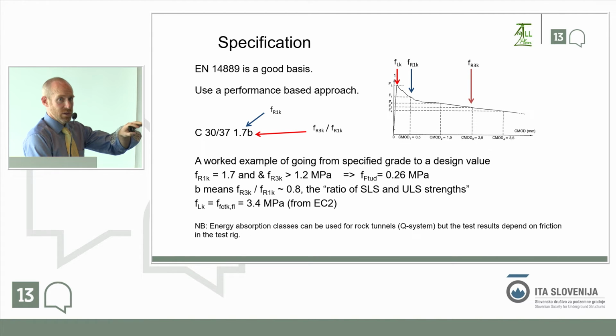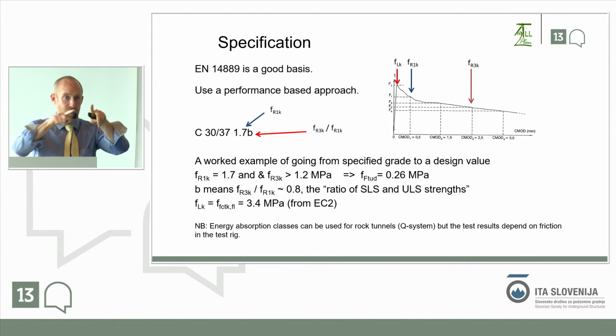So that's 1.7 in this case. And then in terms of this slope, we call it a class B. So that means that the minimum strength at FR3K would be 0.8 times 1.7. So a nice simple way to specify a performance requirement for the contractor. What does that mean when you turn it into capacity in your design?